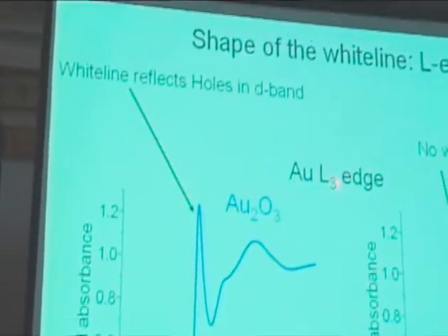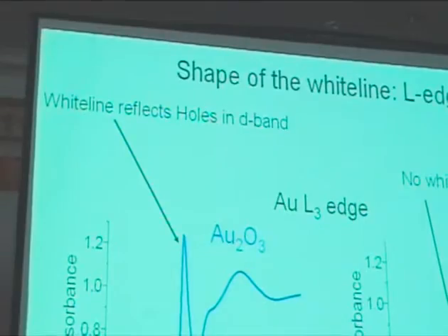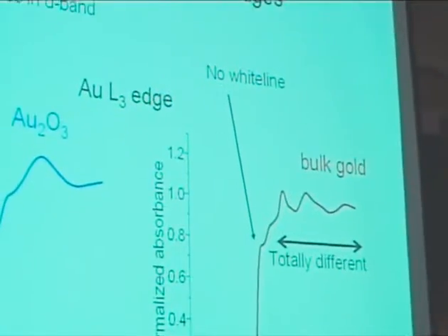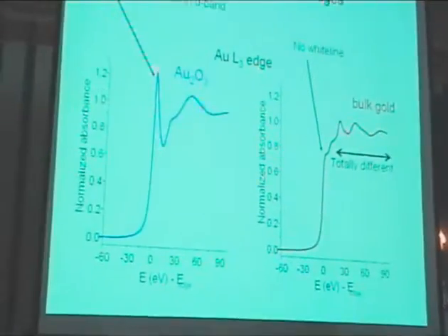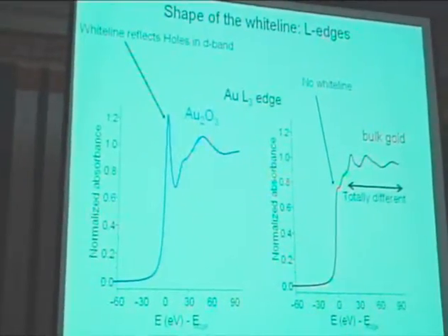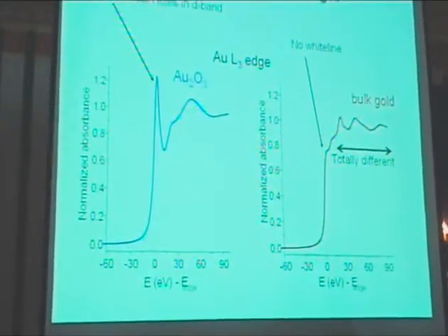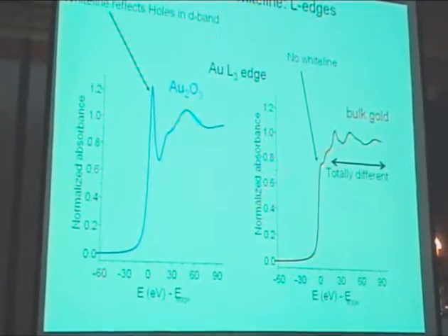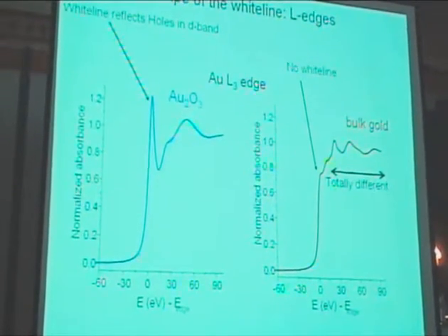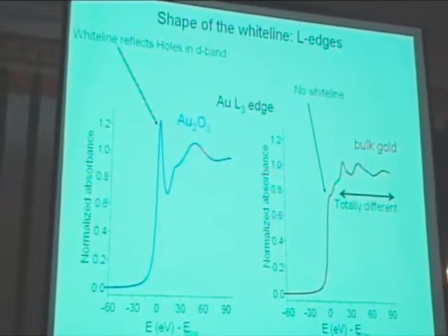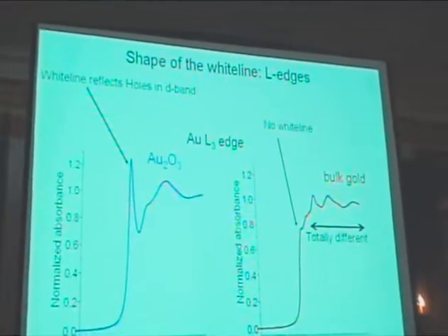And so there is a lot of research now suddenly on gold. And if you go to the gold L3 edge, which means you kick out the 2p electron, and if you would go further, you would go to the EXAFS, but if we just look right at the edge, you see what is called a white line. Since the days of photographic paper, this is called white line, because on the photographic paper, it's the reverse color. So in this case, the strong intensity gives you white line. That's the name.